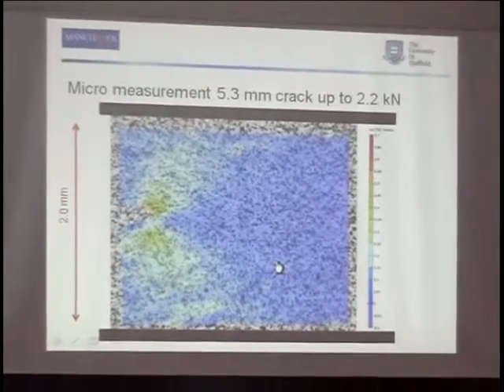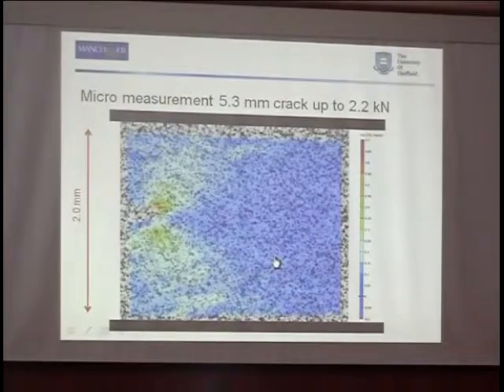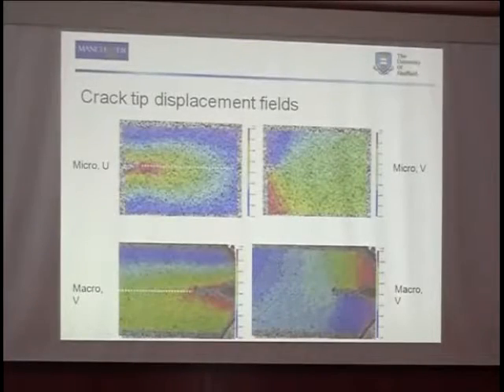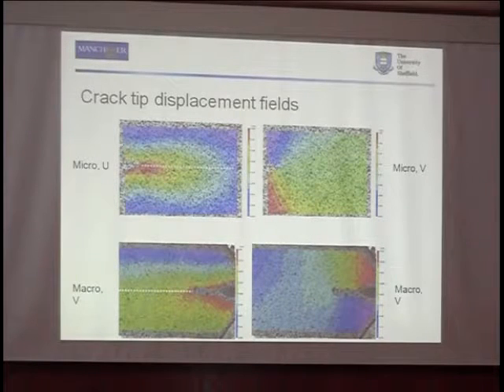So you can see from the micro measurements that it's significant, and you can measure the plasticity around the crack, and even for a fatigue crack, there are significant amounts of plasticity. This is just a snapshot of the displacement field at 2.2 kilonewtons for both micro and macro fields. This is for the same specimen, that's on one side and that's on the reverse side.